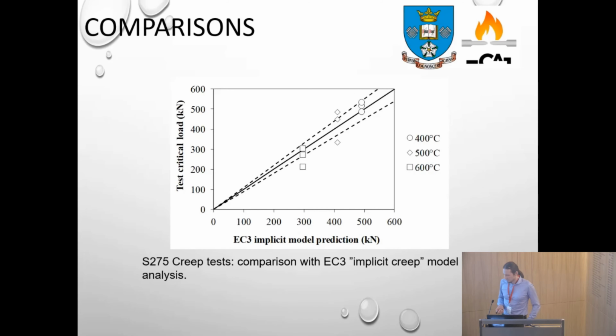When it comes to the comparison using the implicit creep model, the 2% yield strain model, you can see that the safety level of that kind of model at 400 degrees is all right because it falls within the plus minus 10% variation in the prediction. At 500 degrees, you can see that the level of safety is somewhat lowered, so that kind of model cannot capture the critical load that was obtained during the test in comparison to the simulation prediction using this kind of stress strain model. And when we arrive at 600 degrees, you can see that these dots are slightly moving towards the unsafe side. So there is a need for further consideration of the creep component when it comes to the behavior of steel columns.